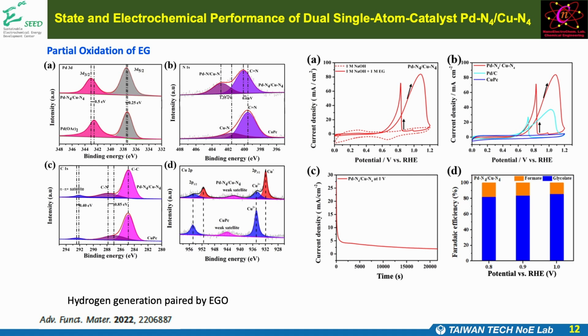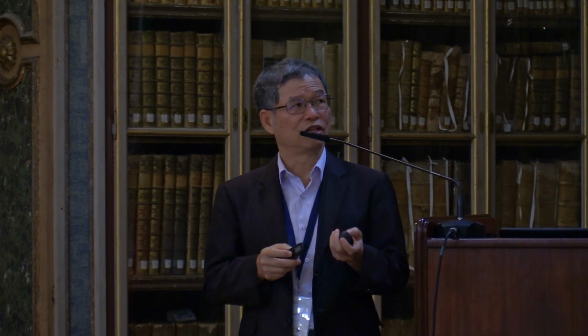this ethylene glycol oxidation. The main purpose is to get intermediate species like glycolate, which has a higher value. In this example, we can get around 80% Coulombic efficiency of the glycolate during this ethylene glycol oxidation. But at the cathode side, we still get the hydrogen, so that we can get hydrogen and also get glycolate at the anode compartment.